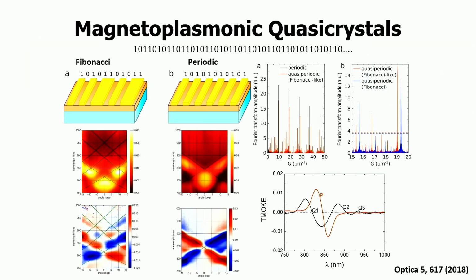In the magnetoplasmonic application, we showed that by arranging these gold gratings in terms of a Fibonacci series, we can get basically three different peaks compared to a periodic structure in which there is only a single peak here. Right. So the periodic is here, and then Q1, Q2, Q3 are the quasi-periodic peaks which we have. So you can get multiple bands. You can design these structures to have plasmon-mediated magneto-optical enhancements.